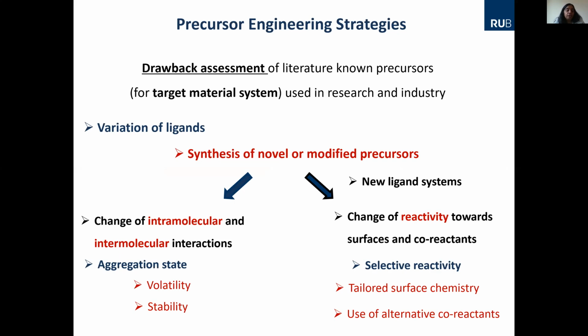On the other hand, if we want to get over the drawbacks, then we have to do a systematic engineering of the molecular chemistry, and that is one part of our research. So we look for different ligand systems, we modify the precursors, see whether we can influence the volatility, stability, reactivity based on the intramolecular and intermolecular interactions within the molecule, or also change the reactivity, tailor the surface chemistry, or use alternative co-reactants. Sometimes to make oxides, the molecule may not react with just water or oxygen. Then you have to go to ozone, a very harsh medium, but nevertheless, that's the only means to get a good reactivity.